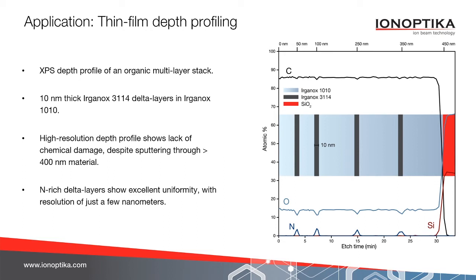The GCIB 10S is capable of sputtering through this very soft material without breaking bonds, and this is evident in the smooth line that we see for the carbon signal. We also see very strong, very clear peaks in the nitrogen signal as the Irganox 3114 layers appear. So the uniformity of the nitrogen signals is not changed despite etching through more than 400 nanometers of material. So there is no damage being imparted to subsurface layers. So the GCIB 10S is a very powerful tool for depth profiling of this nature.